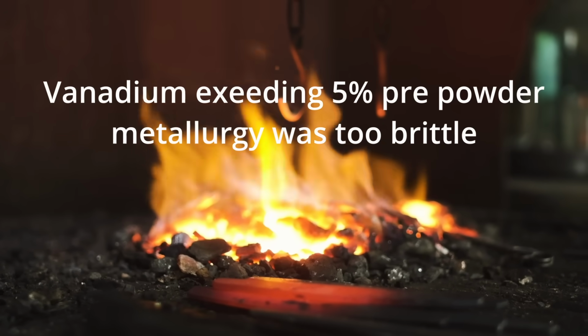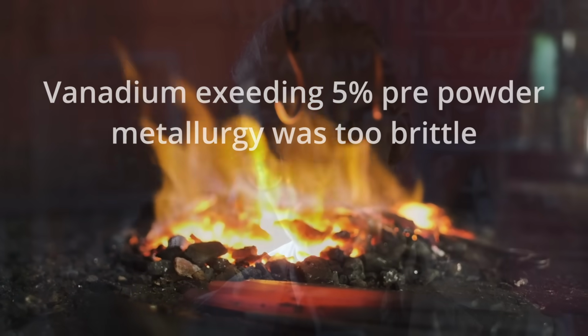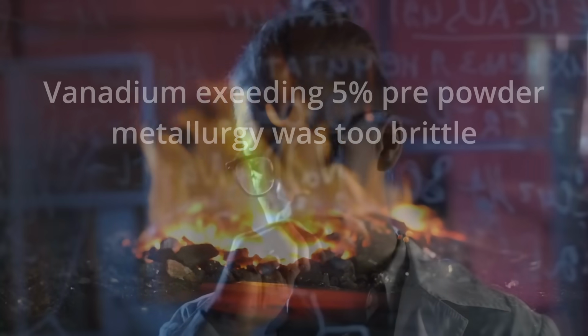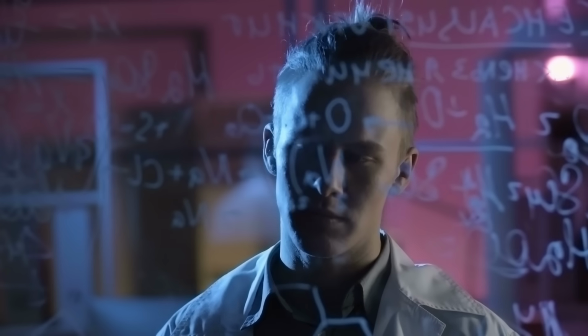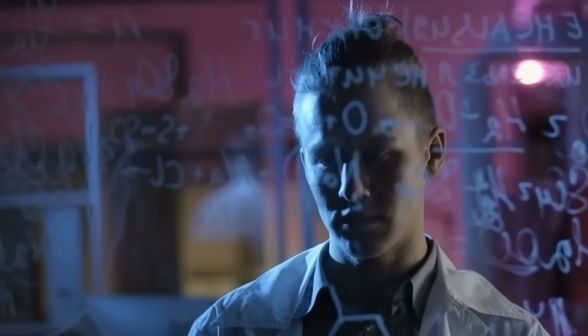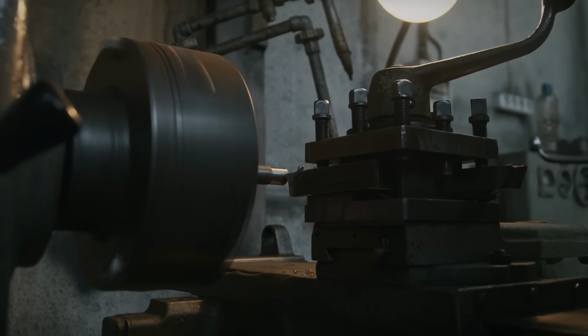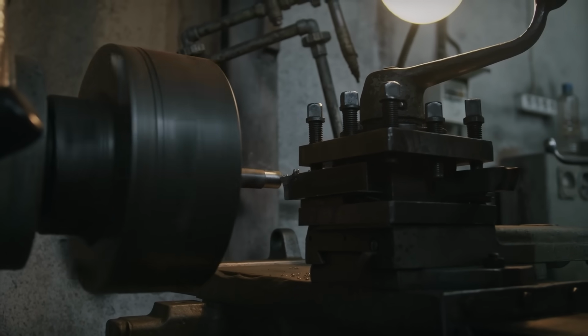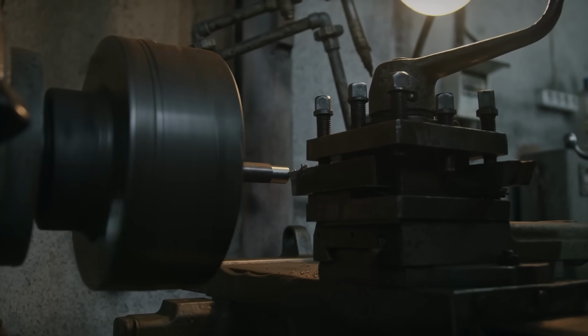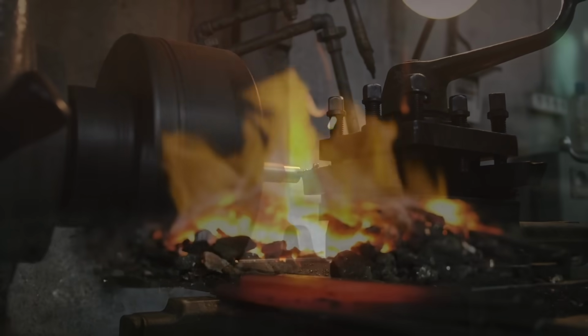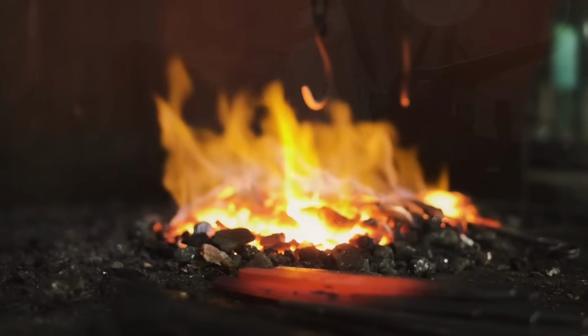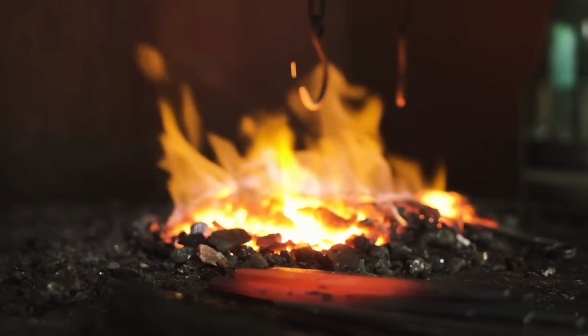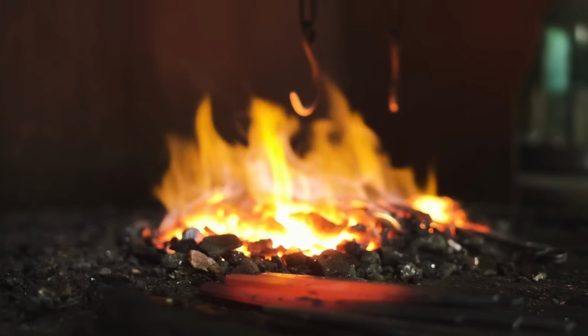To clarify further, steel compositions containing more than 5% vanadium were considered so brittle it was determined that the steel would crack during forging, effectively halting metallurgists' efforts to use higher amounts of vanadium to achieve higher levels of wear resistance. That was true until about 1967, a time when Crucible Industries was alive and well, and oh yeah, they were also filing the patent for their powder metallurgy process. Powder metallurgy effectively took the old rules and chucked them out the window.